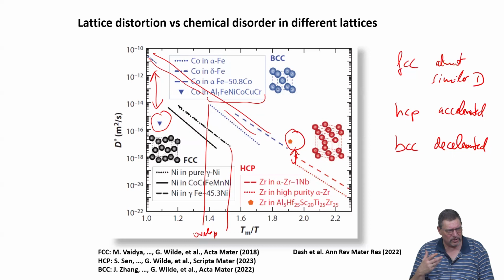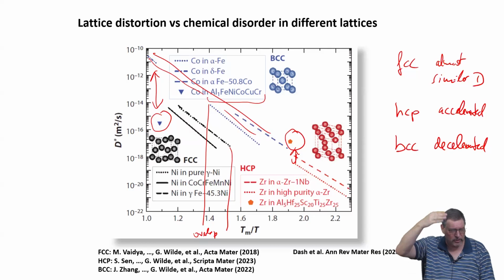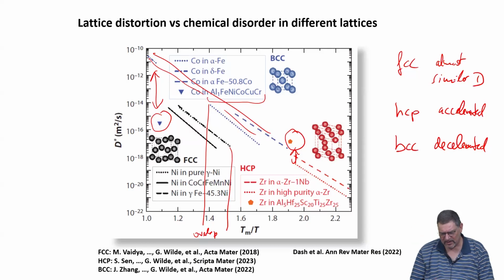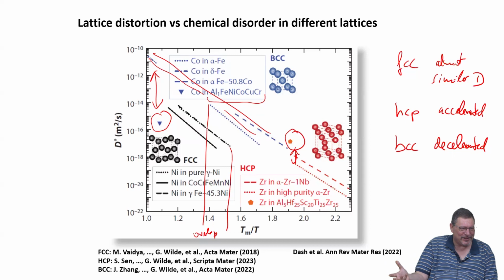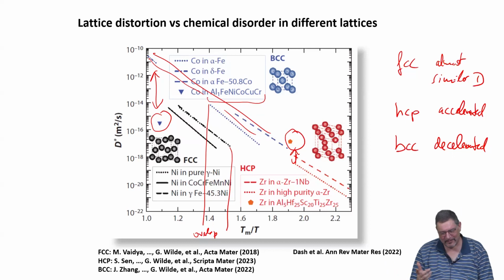If there would be a change inflicted by temperature, we would see at least a kink, a different slope in Arrhenius representation, even a jump could happen. It's not the case here, so I would say there is no real indication of any disruptive change based on lattice changes or anything like that. Why it is different in FCC, BCC, HCP is very difficult to discuss because the chemistry is also different, right? Otherwise, if the chemistry is no different, how do you change the lattice structure, right?